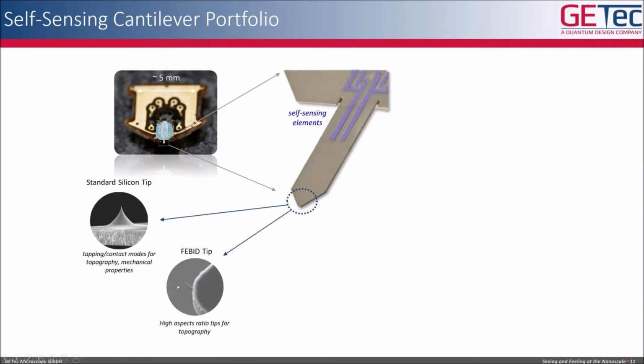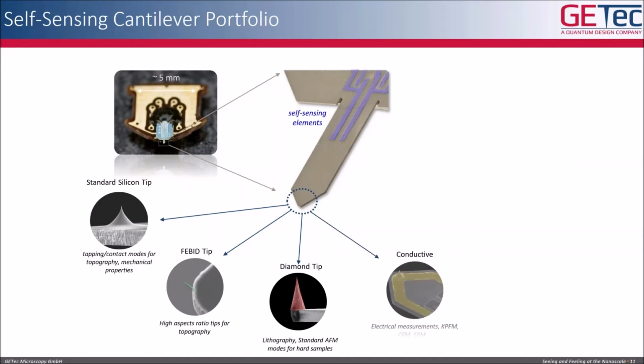But we can also offer these FEBID-grown, high aspect ratio needle-like tips if you, for instance, want to measure in deep trenches. Then we also have a pure diamond tip, which is extremely robust and works extremely well with wear-resistant surfaces. With hard surfaces, you can even use it for lithography or measure very hard sample surfaces without the harm of damaging your tip.